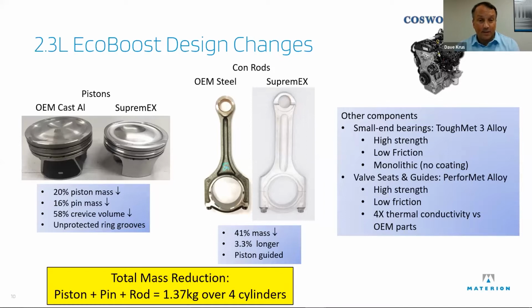The connecting rod was a big change because it was steel going to an aluminum product. You can see that it had to be made a little bit beefier, a little bit thicker to get the same stiffness. But at the same stiffness, it was 41% lighter than the original rod, and it had to be a little bit longer. As you see, the piston is shorter to maintain the compression height, so we had to make the rod longer. That does reduce some friction and some side loading, and it was piston guided.